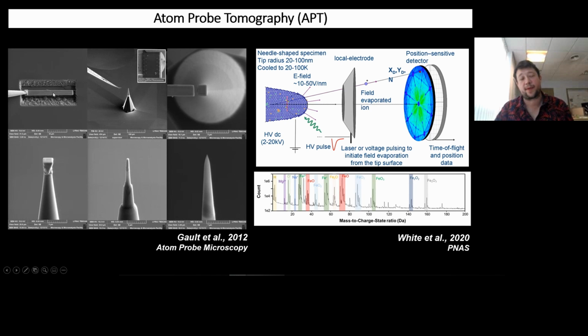So we protect our surface. You can imagine your baddeleyite or your apatite will be under here somewhere. We go in with the micromanipulator. We cut it all around, and then we attach it with a micromanipulator and lift it out. So we've isolated that in 3D and then plucked it out. It's almost like nanosurgery, microsurgery on rocks, which is really fun. We come out with our lift-out and we park it on a silicon post.